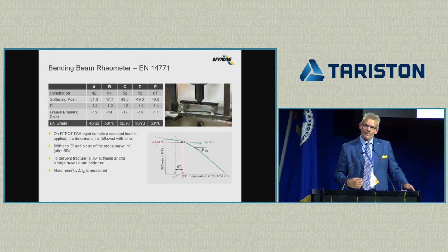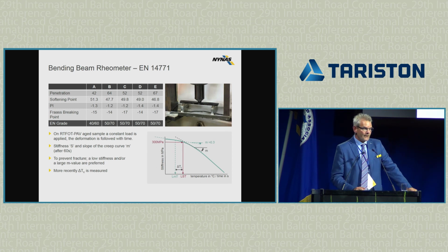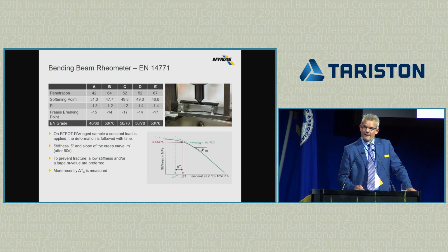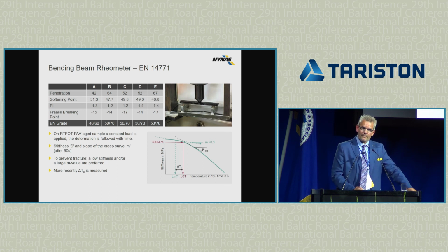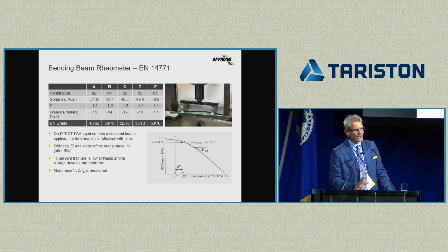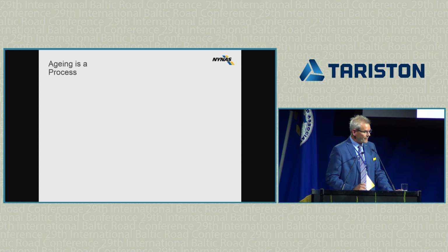Now, this parameter is not measured on fresh bitumen. In actual fact, this parameter is measured on bitumen that has been aged, not just short-term aged, but also long-term aged. Short-term aging is part of the European specification, but long-term aging is not part of the European specification for bitumen. Now, aging is not a property of a material, but aging is a process.